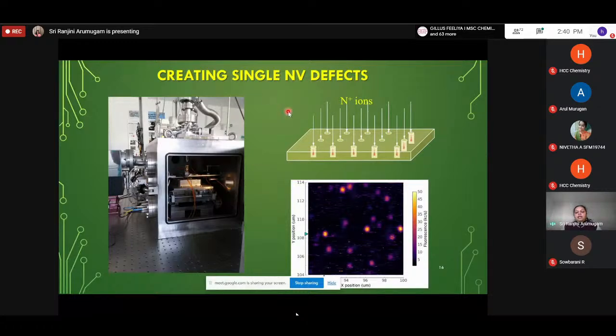So we take the ultra pure CVD produced diamond in a plasma chamber and impinge it with nitrogen gas. The ratio of nitrogen to carbon is optimized now, so you can selectively choose how many nitrogen vacancy centers you want to create. So you impinge it, knock out some of the carbons and replace them with nitrogen. And this is a fluorescent image of the nitrogen centers. These bright spots are nitrogen centers.